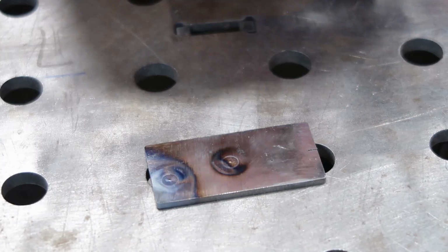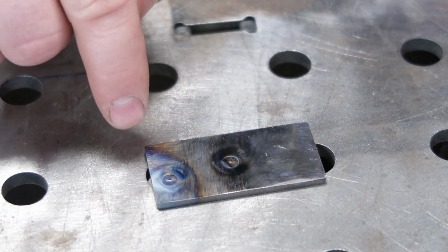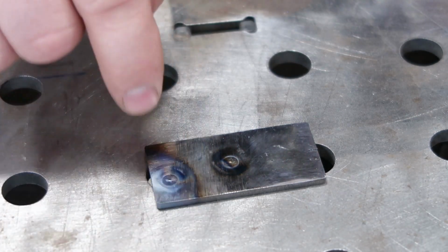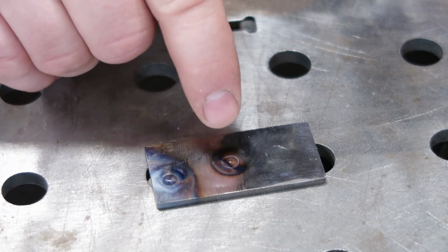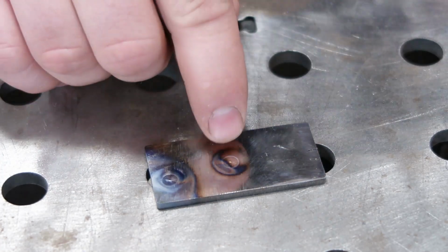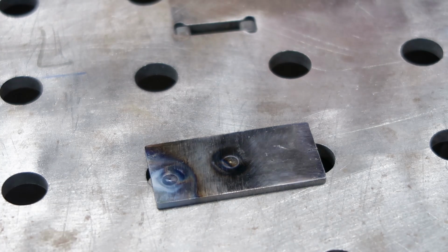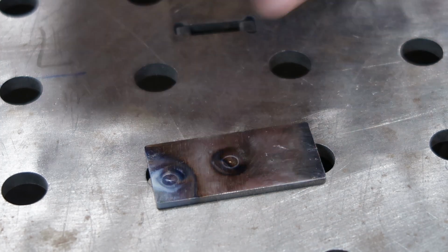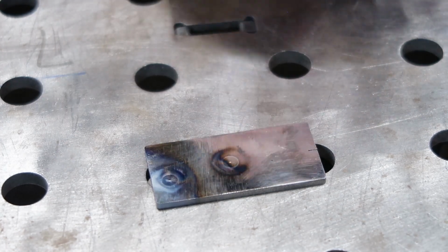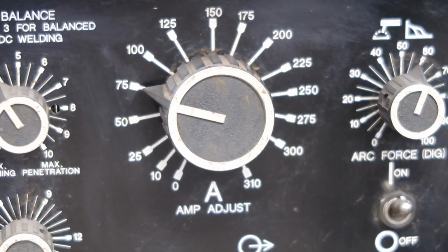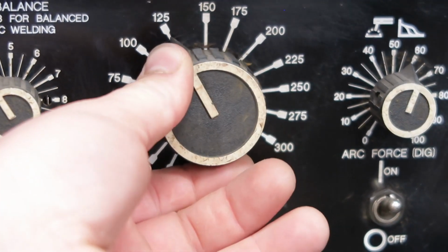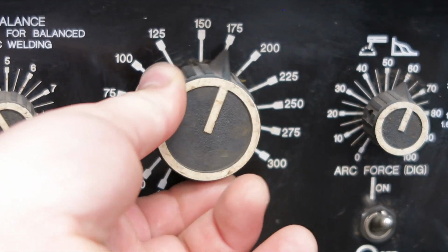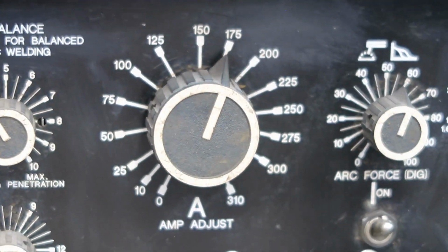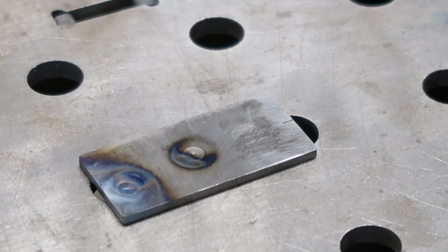So you can see we held there for a longer duration, and you can see this heat signature is much greater. This is at 75 amps and this is at 125 amps. Now let's go to the rule of thumb that I'm suggesting. With our 125 thousandths, we're going to turn our machine to 125 and then add 50 amps to that. So when we come down here to 125 and then add 50, that puts us right at 175 amps. Let's see what happens.